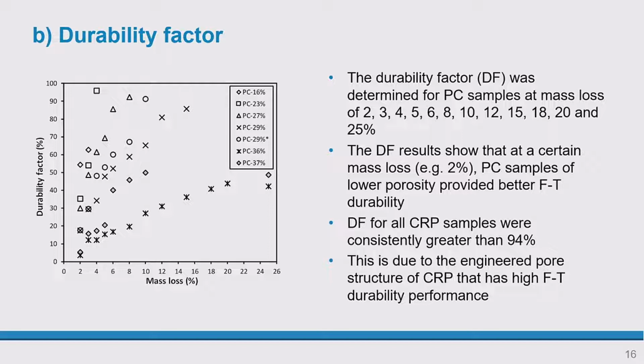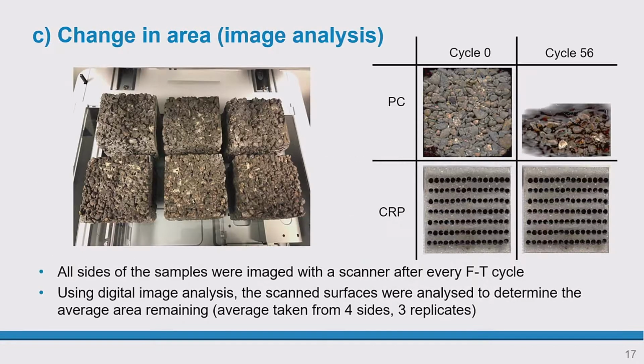But for the conventional systems, we plotted the durability factor against mass loss. So for example, for a 2% mass loss, we compared, depending on the porosity, what the durability factor would be, which obviously the lower the porosity, the higher the durability factor, because it meant that it's a much stronger mix and you don't get this cracking and spalling of the aggregates from the cement paste.